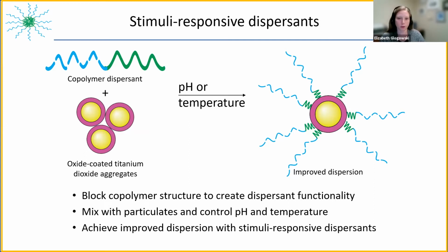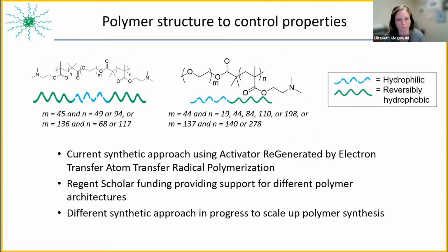And so with our stimuli responsive polymers, they adapt to whatever particulate coating is in play. And so our specific polymers are both pH and temperature responsive. For this application, we're looking specifically more at the pH responsive aspect because of the different surface coatings. But ultimately, based on the polymer structure, we can tailor the response of the polymers to make sure they're the ideal dispersants. Next slide, please.